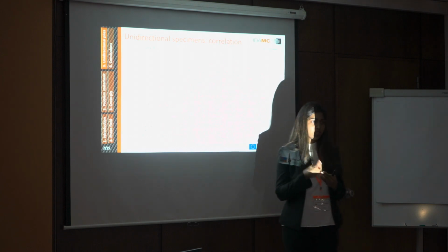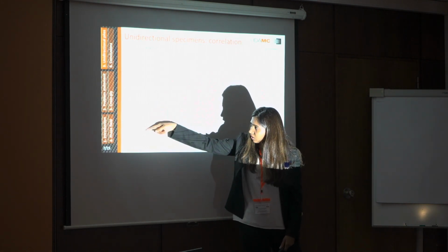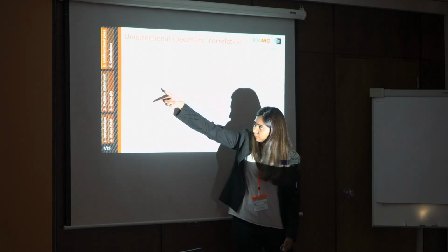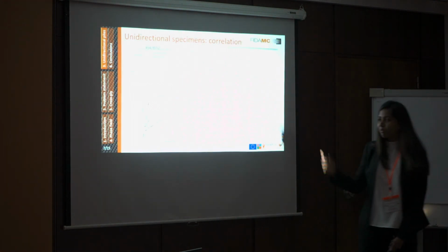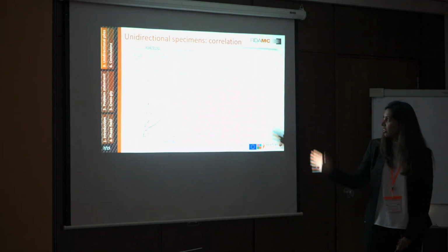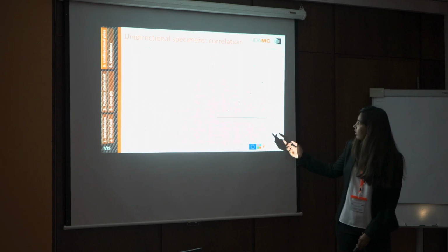So that's what we did for our samples with 8 plies, 16, 24 and 32 plies, and then we obtained these stable moment versus rotation curves with the snapback behaviors for all the samples. Then we took the peak moment values and we compared them with the experimental values and they matched perfectly well.